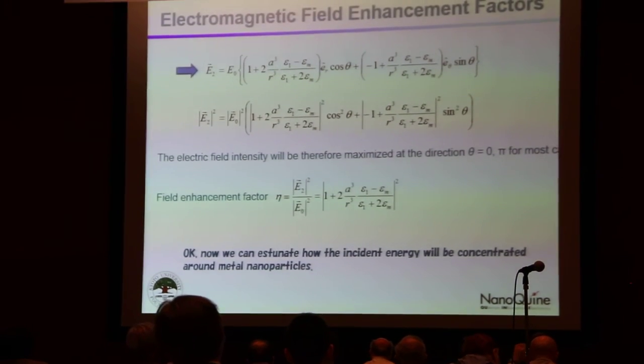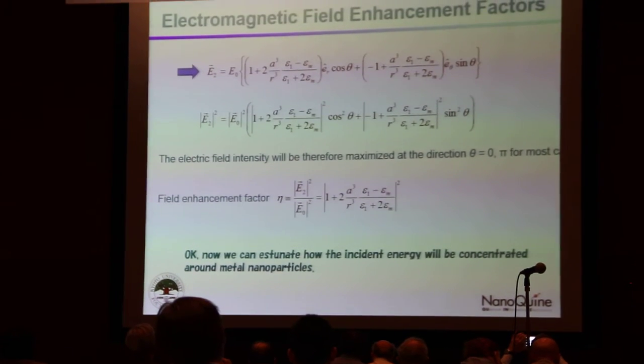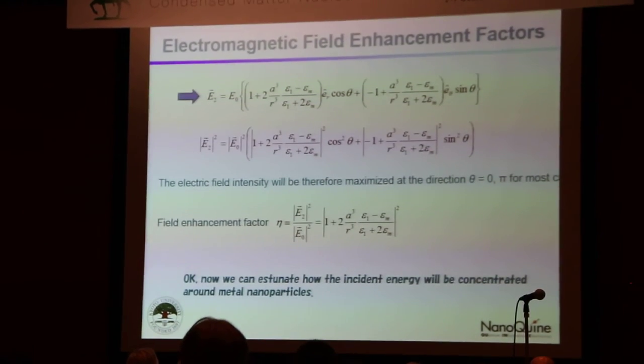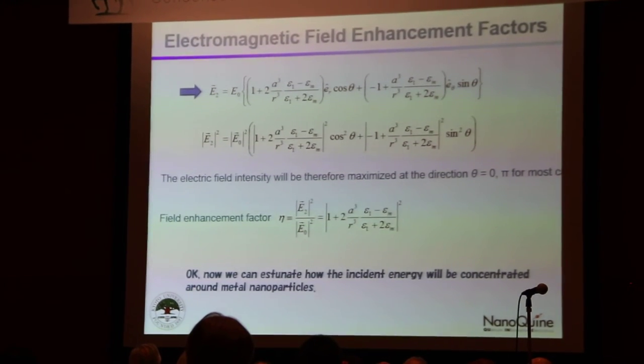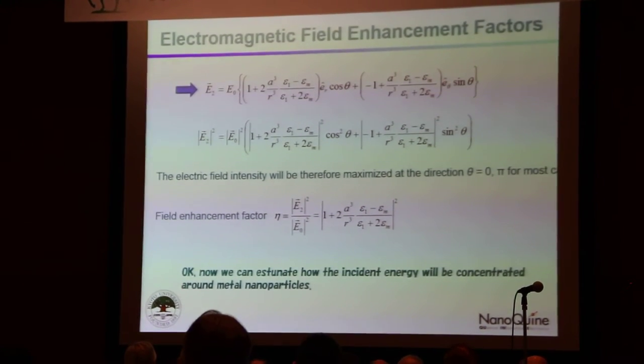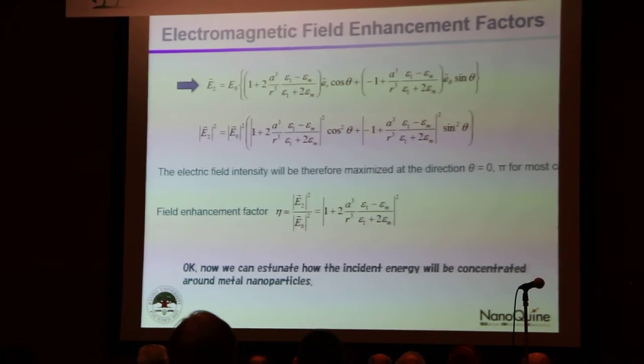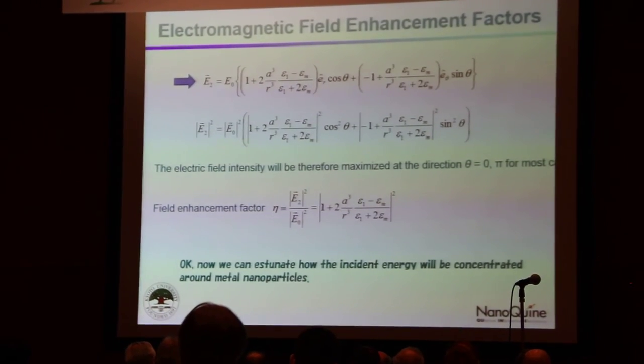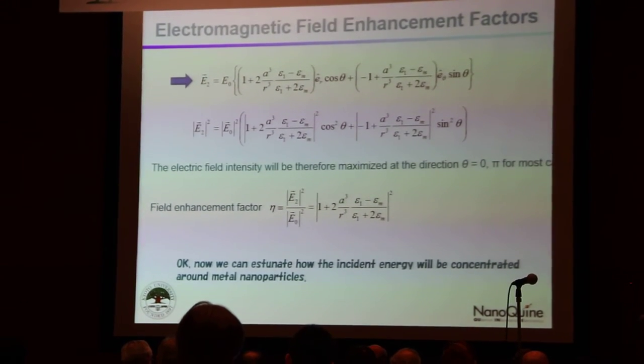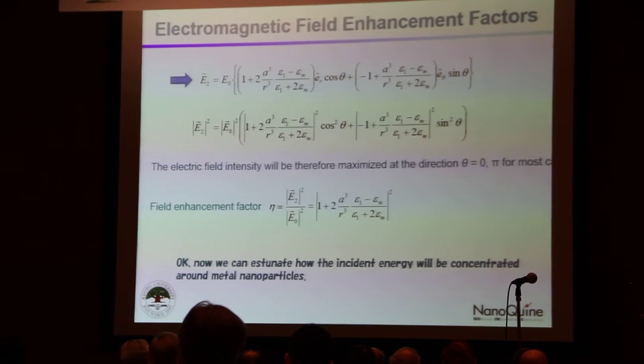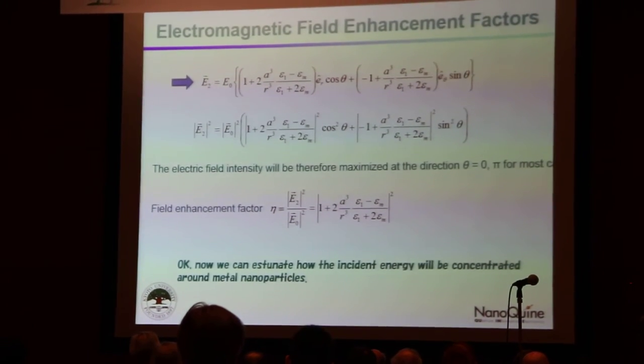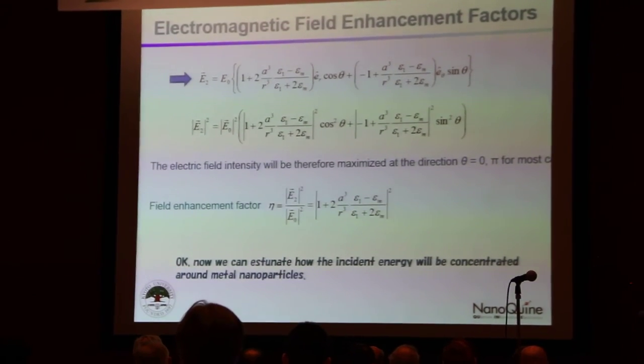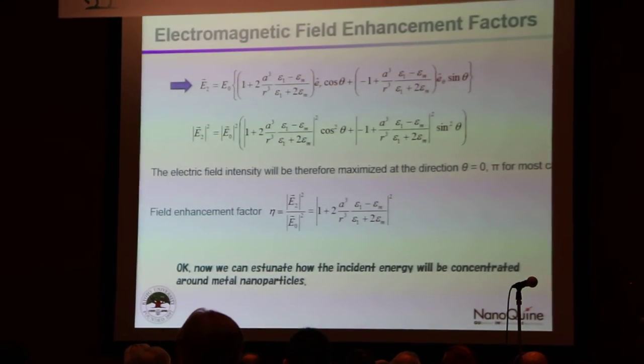By simply taking a ratio we can know how much energy or optical field is enhanced by the presence of the nanoparticle. The key of this enhancement is the surface plasmon — the strong correlation between the incident field and the metallic free electrons through oscillatory movement of free electrons inside the metallic substance. This phenomenon is particularly enhanced for nanoscale metallic particles whose dimension is similar to the incident wavelength.